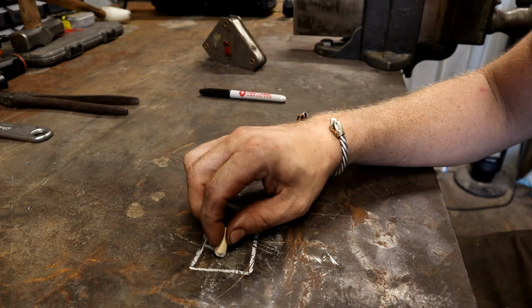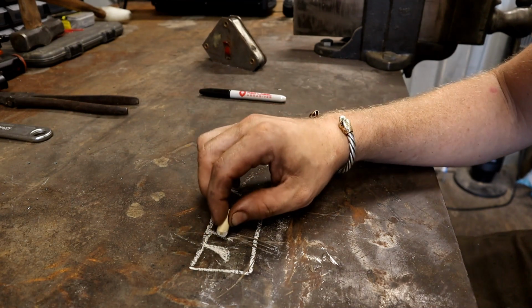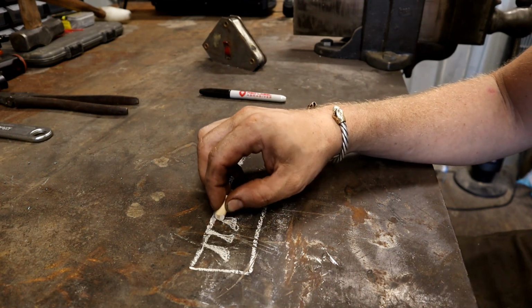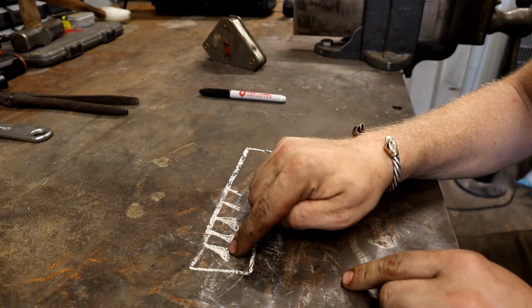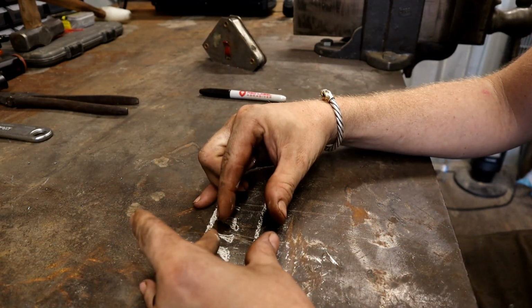They actually exploded and got a little, like in the bottom of the beam of the plasma, it burns a little harder. So I was essentially creating these little dovetail shapes, right? So my material, when I start hitting down on it, was immediately closing in on itself, trapping the hole here, and nothing was really getting all that compressed, right?